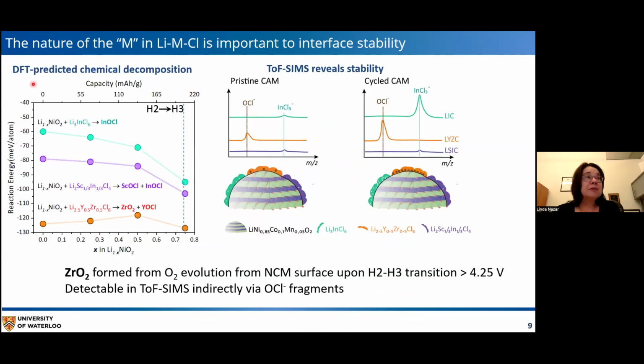So in my group, we carried out these DFT predictions of chemical decomposition, and we used lithium nickel oxide, or charged lithium nickel oxide, as a representative for NMC because we can order the structure. And we then compared the lithium indium chloride, the LSIC, and the yttrium zirconium. And you can see that the reaction energy at the interface to form either the oxychloride or the zirconium oxide is negative in all cases, but it is definitely most negative for the yttrium zirconium chloride. This is the point at which the NMC undergoes its H2 to H3 phase transition, and evolves oxygen.